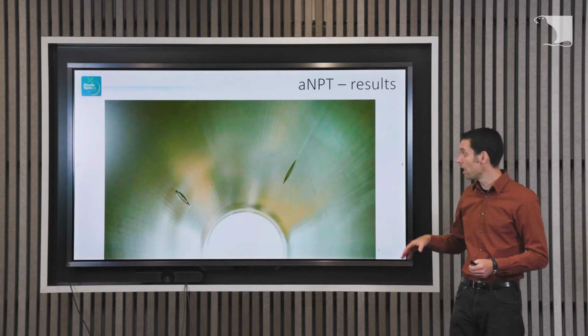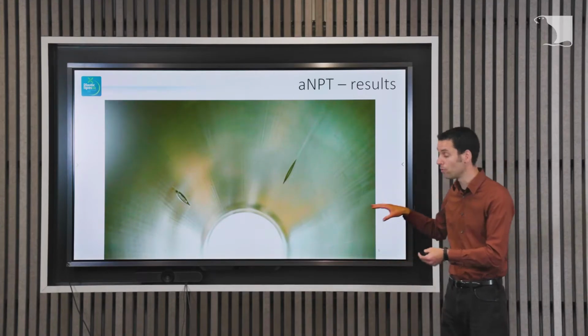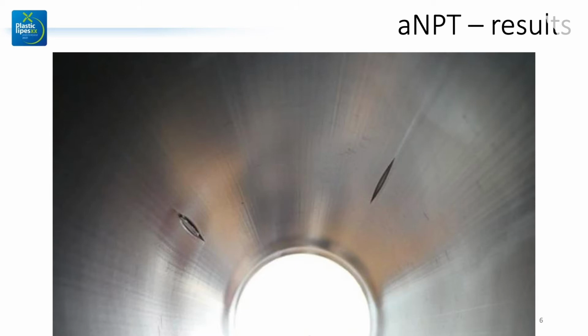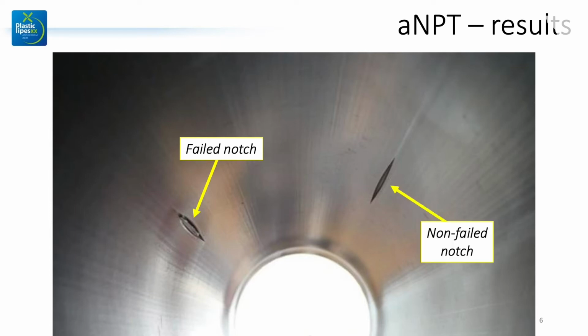So what about some results? Well, here I show you a picture of a failed notched pipe test, accelerated notched pipe test. It's made from the inside of the pipe. So we're looking at the inner wall of the pipe and we actually see two notches, which is sort of strange on one hand because the notches are made on the outside of the pipe. But now we see the notches on the inside. Of course, it makes sense if the notch failed, but the other notch we are seeing did not fail. And the other two, because there are 4 notches, we couldn't see on the inside of the pipe. So that seemed to be interesting.